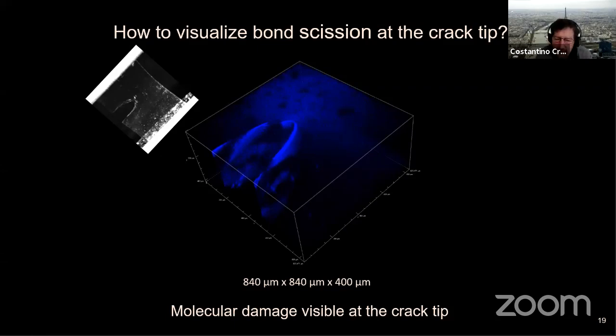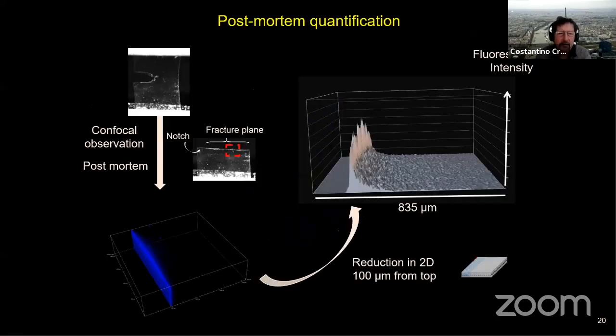So what we did at that point, we said, well, this is an open crack. It's not going to be very reproducible. We have to make it with a blade. No two blades are the same. Maybe it would be much better to look at crack propagation. So crack propagation should be more reproducible. We open the crack until it propagates, and then we look at the fracture surfaces. The molecule, once it's broken, is permanently fluorescent, so we should be able to quantify these molecules after the sample is broken. So indeed, this is what we did.